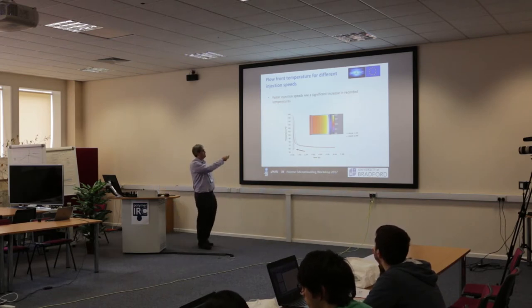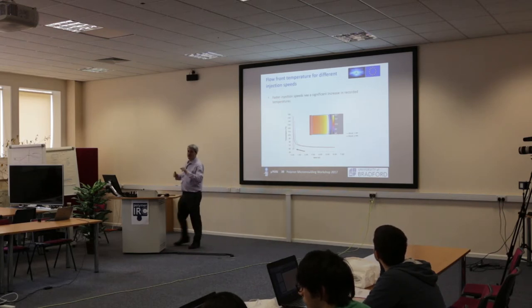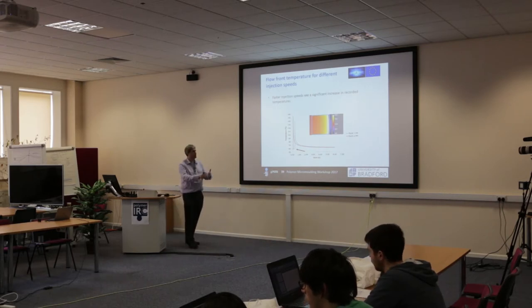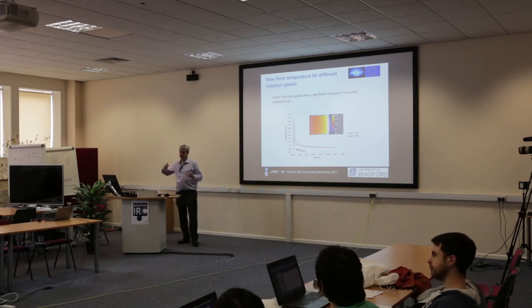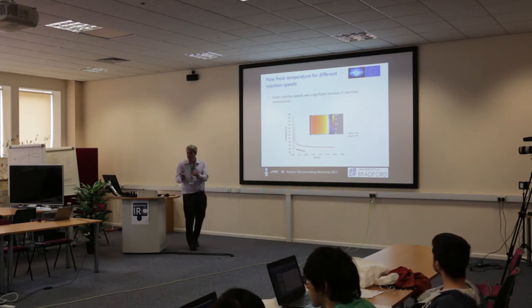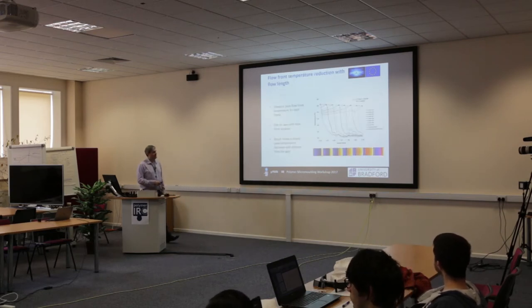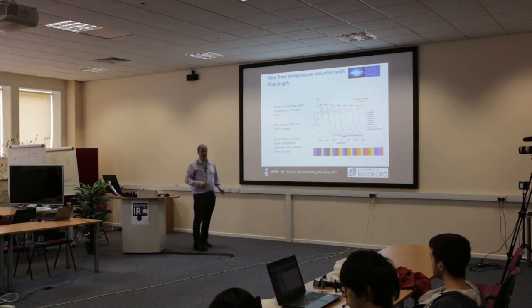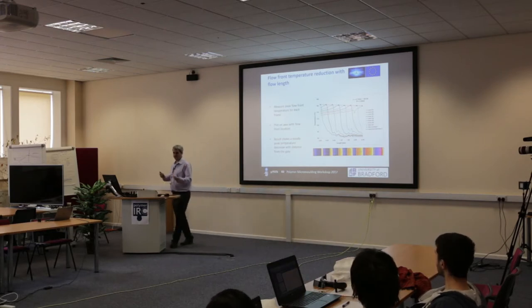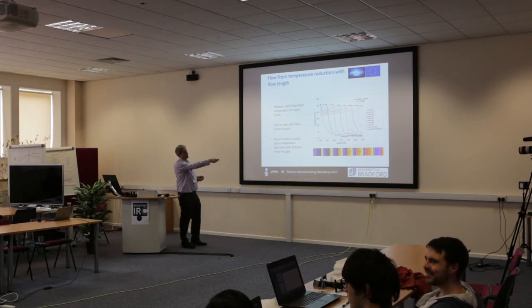As you would expect, if you run at a faster injection speed you see a higher surface temperature, for two reasons: first, the material has less time to cool as it enters and travels through the mold; second, there may also be a shear heating effect because forcing material in quickly generates internal friction which also contributes to the temperature increase. Likewise, looking at surface temperature evolution along the length of the mold, we see surface temperature decline — caused by additional cooling of material being convected through the center of the part as it's distributed onto the cavity wall.